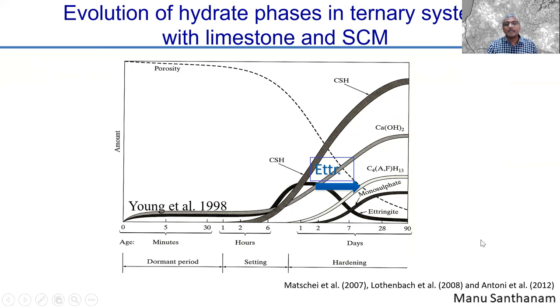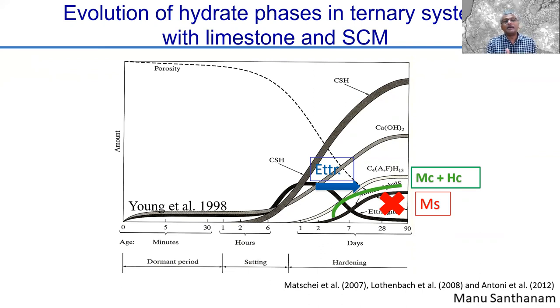So what happens here is, because the sulfate now is competing with carbonate to react with the aluminate, the sulfates that led to the formation of ettringite remain stable, and the ettringite quantity does not really go down. Ettringite remains stable, so you don't really get any monosulfate formation. On the other hand, you start forming what are called monocarbonate or hemicarbonate, which are basically the reaction between carbonates and aluminates. That leads to formation of monocarboaluminate or hemicarboaluminate.